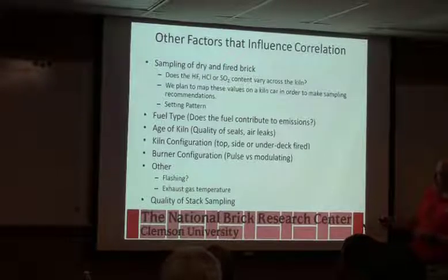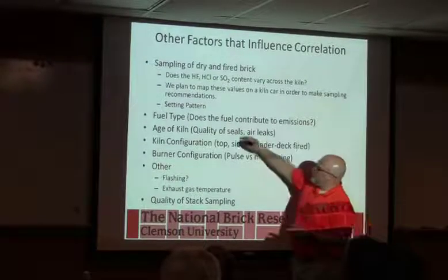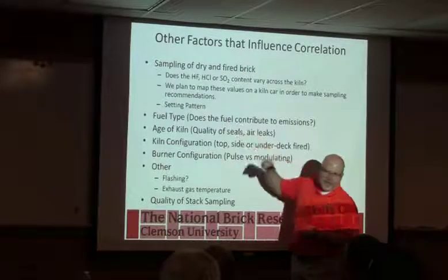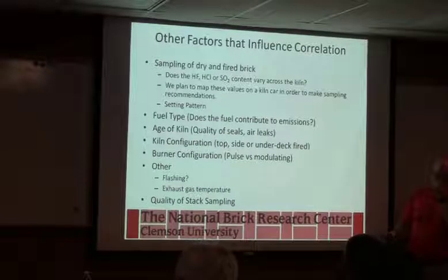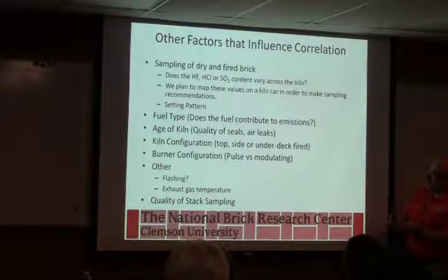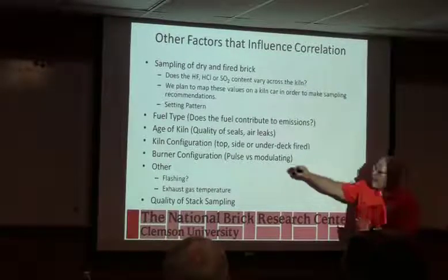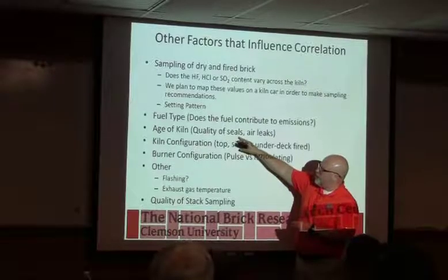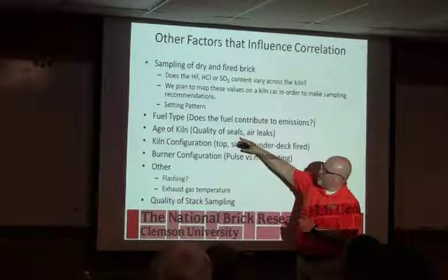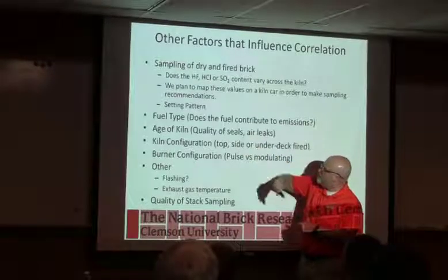Fuel type, does it contribute to emissions? We don't think that it does for fluorine and chlorine. Obviously, if you're using a solid fuel or something, it could contribute to sulfur emissions, but we don't really see much influence from fuel type. Age of the kiln, how much leakage there is, how much air infiltration, seems to be the big issue that affects our correlation.